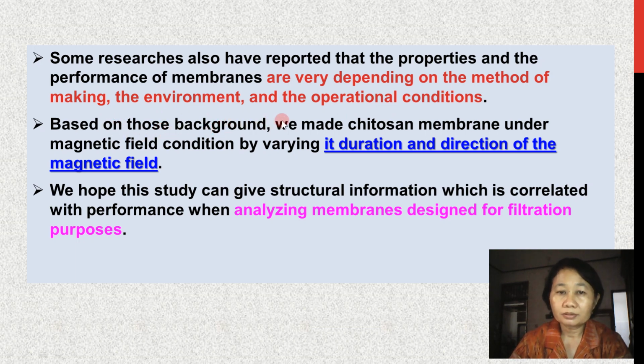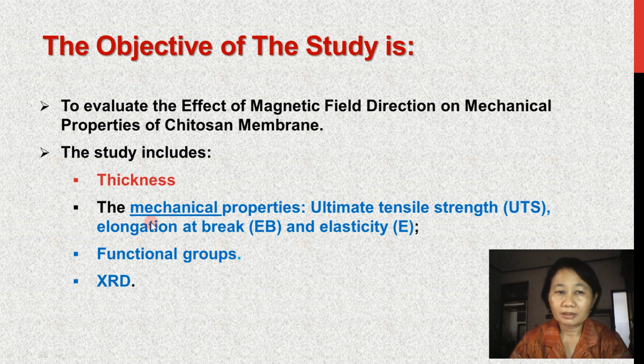Based on this background, we made chitosan membranes under magnetic field condition by varying the duration and direction of the magnetic field. We hope this study can give structural information which is correlated with performance when analyzing membrane design for filtration purposes. The objective of this study is to evaluate the effect of magnetic field direction on mechanical properties of chitosan membranes. The study included thickness. The mechanical properties of the membranes include ultimate tensile strength, elongation at break, and elasticity of the membranes. Also, we have studied functional groups and X-ray diffraction.